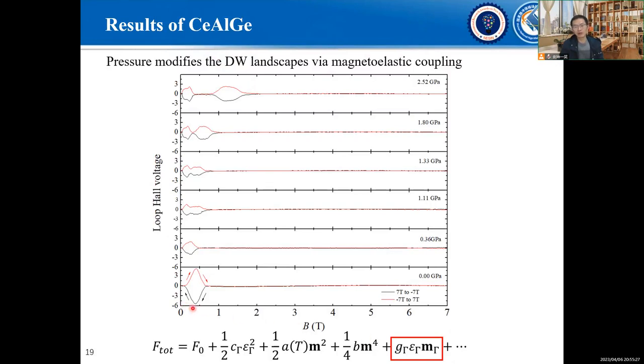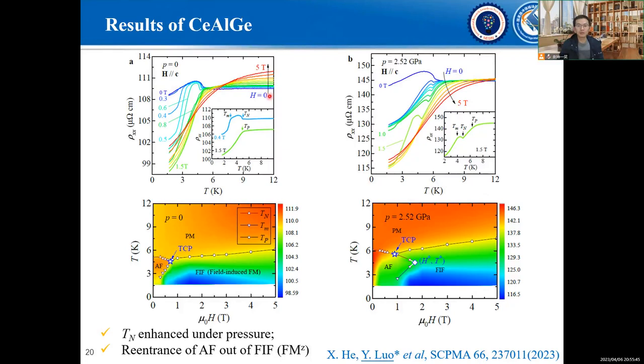And indeed, we found that the loop shift topological Hall effect changed quite a lot with pressure. Especially under high pressure, the region of the loop actually splits into two. And we will explain the reason later. Before we get into the origin of the loop shift topological Hall effect, now we show